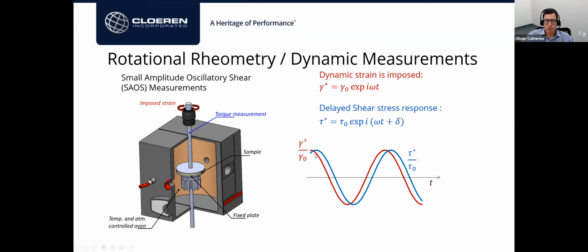So this is a representation of the strain and the response in shear stress for the material. And the main thing is that as we impose the strain, we are going to see a delay, a shift in time for the response in shear stress, which is shown with this delta value. And from there, we can derive many viscoelastic parameters that are quite interesting.